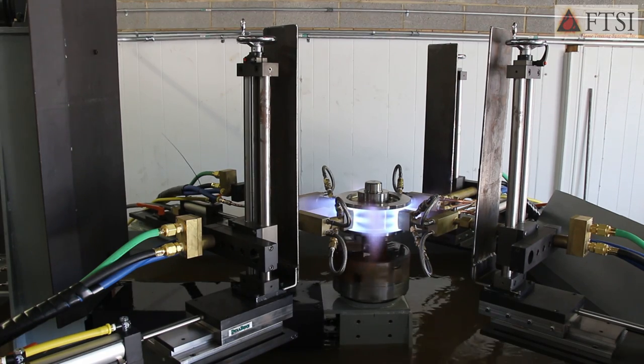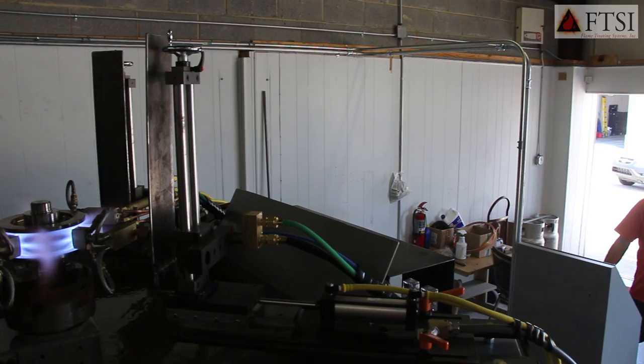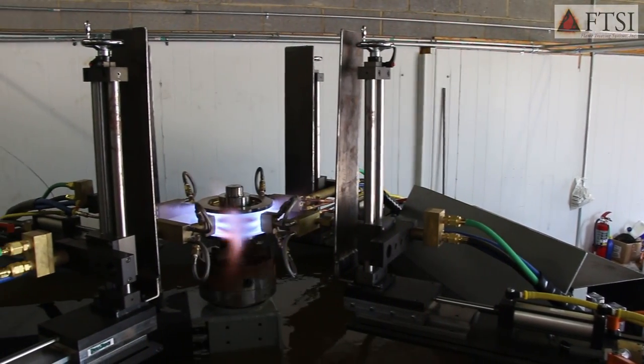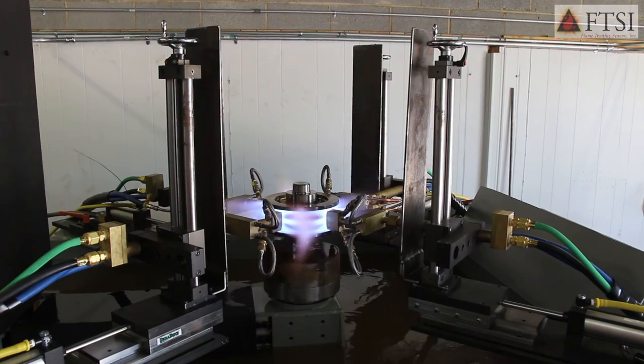on the crane wheel. And the quench itself is critical because depending on the material that you harden, you have to possibly have polymer added to the water. The temperature of the water of the quench needs to be maintained. And so all those things are being taken care of on this spinning machine along with the controls that are required so that you can come back to the correct flow rates of the fuel and oxygen, which is extremely critical for consistency.